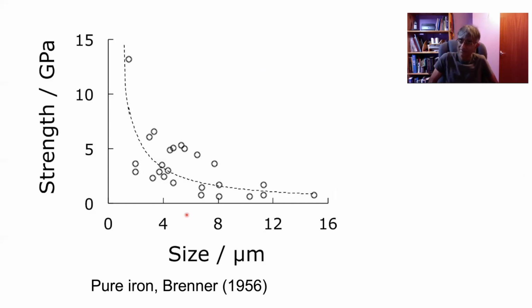Once you have enough dislocations in your structure, then the plastic flow stress becomes a lot less than the ideal strength of the crystal, which involves ripping apart layers of atoms. But we are very close here to the ideal strength of iron in tension. We could get to something like 22 gigapascals in tension if we had the perfect crystal of iron and if that crystal of iron was small enough. Now, that's a very important point.